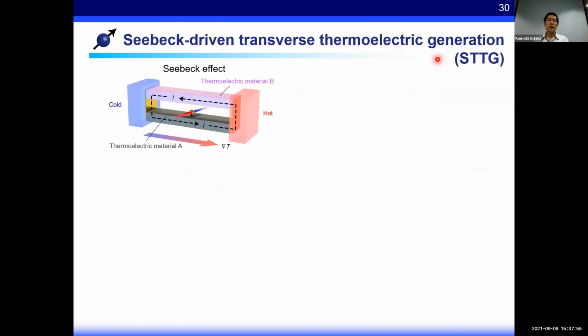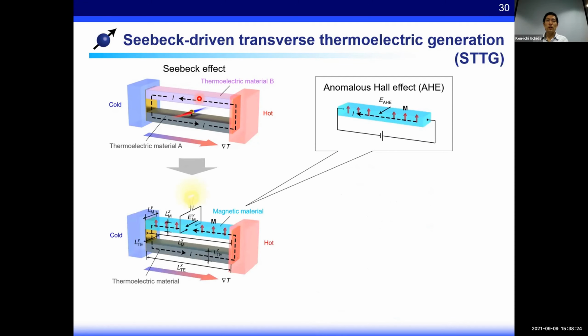Here, please imagine a closed circuit comprising two different conductors. When the temperature gradient is applied to this circuit, a charge current is generated due to the Seebeck effect, which comes from the difference in the Seebeck coefficients between these two materials, A and B. Actually, this configuration was used by Dr. Thomas Seebeck 200 years ago when he discovered the Seebeck effect. We replaced one of the materials in the closed circuit with a magnetic material. Here, the Seebeck-driven charge current is converted into a transverse electric field by the anomalous Hall effect when the magnetic material is magnetized in the direction normal to the plane.